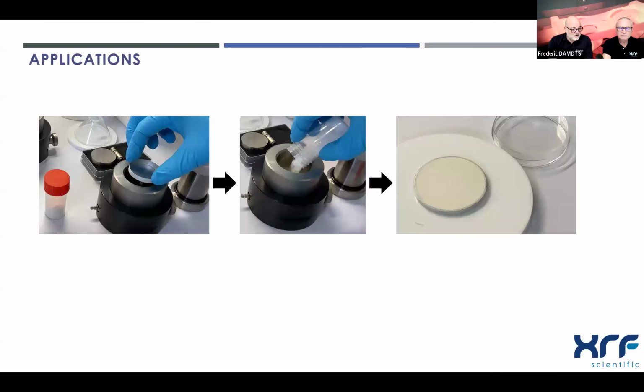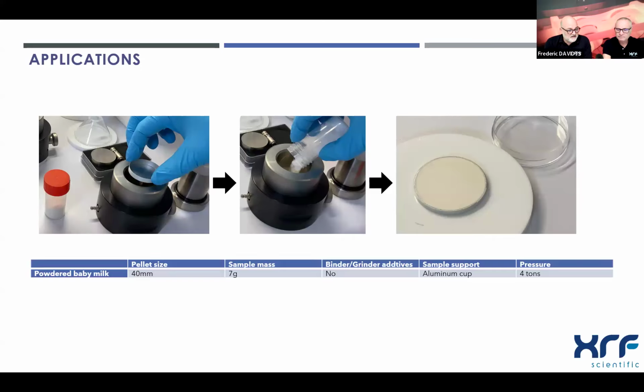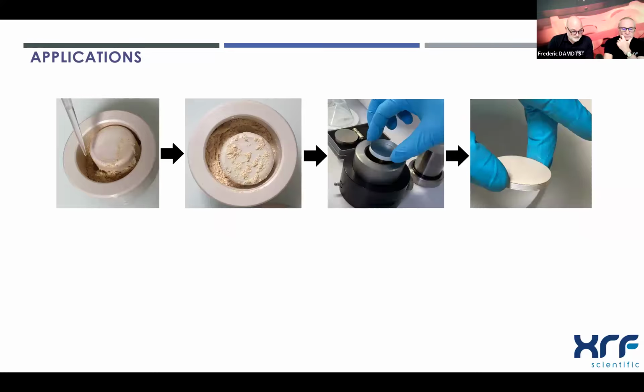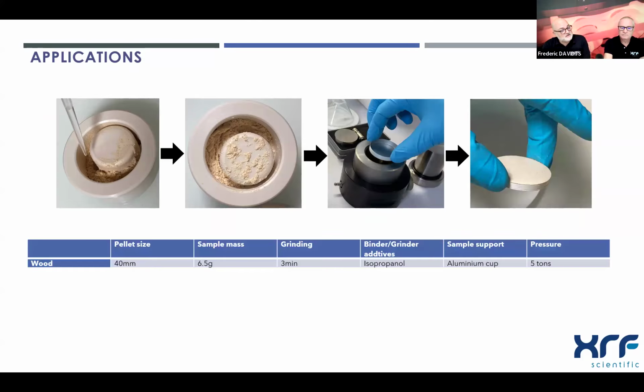Here we gave the case of baby milk powder. Again, really easy in this case. You just feed the die with the milk in an aluminum cup, and then just press at 4 tons, and you obtain a perfect pellet ready for analysis. Here the case of wood. Again, here we need to add a grinding head before the grinding to be able to have wood fine enough to press it. And we use isopropanol. We grind during 3 minutes. Again, we add an aluminum cup, and then we press at 5 tons, and we obtain a very nice pellet of wood sample.